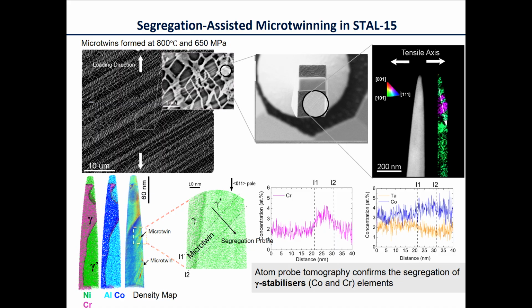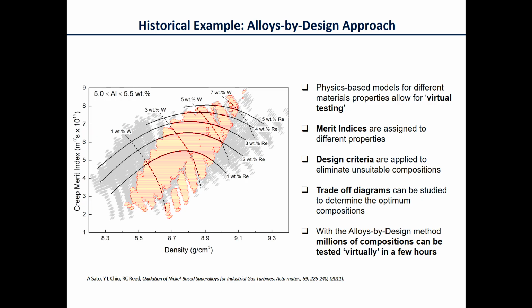These are microstructures of the deformation characteristics of this new alloy, which we found a very special kind of twinning mechanism here, which involved us needing to take needles of the material and then stripping off the ions one by one to identify atom probe maps here, which we could then interpret for evidence of this so-called micro-twinning here. I'll say more about this very neat technique later on in my presentation.